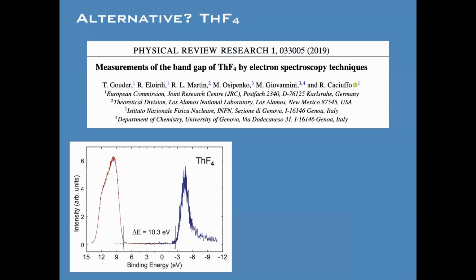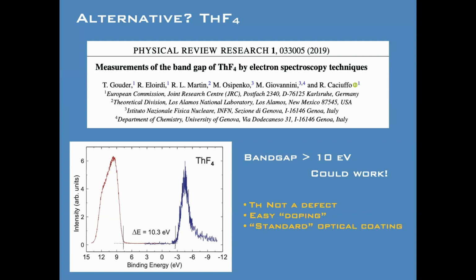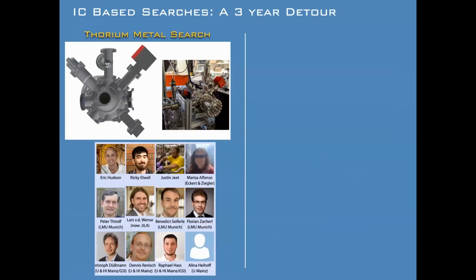But a couple of years ago, mostly led by Richard Martin, from what I can tell, at least that was the initial idea, thorium fluoride was re-examined. And it was found that the band gap isn't 6.5 eV, it's 10 eV, which is a huge difference, and it means this could work for us. This would be wonderful because thorium isn't a defect in this, right? It's easy to dope. And if you remember, it's a fairly standard optical coating. I'll come back to that in a minute.